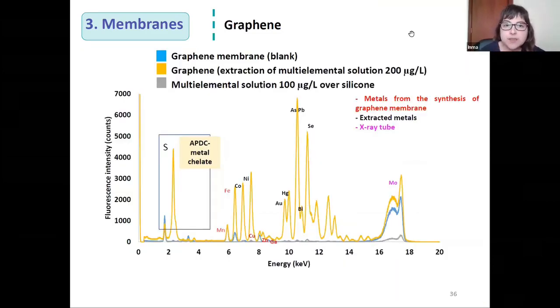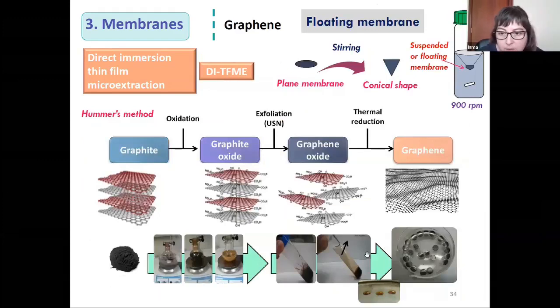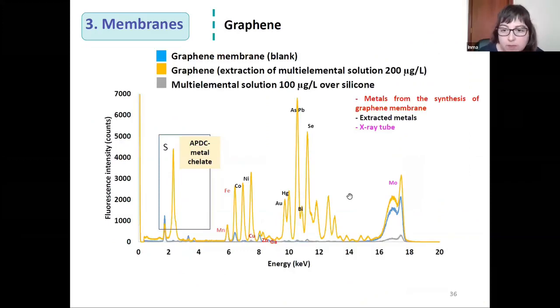In this slide, we can see the spectra obtained for different graphene membranes. As we can see, the background is very low. Additionally, we can see that a sulfur peak is observed due to the presence of APDC as metal chelates. And in black, here we can see the target analytes. Also, we have some elements that appear due to the different sources. For example, the manganese is used as potassium permanganate for the synthesis of graphene from the graphite powder, so because of this, probably we have this peak. Also, the peak of iron could be coming from the drying of the drops, the thermal reduction of the graphene oxide to graphene. Probably the iron contamination comes from here. And also we can see the peak of molybdenum.